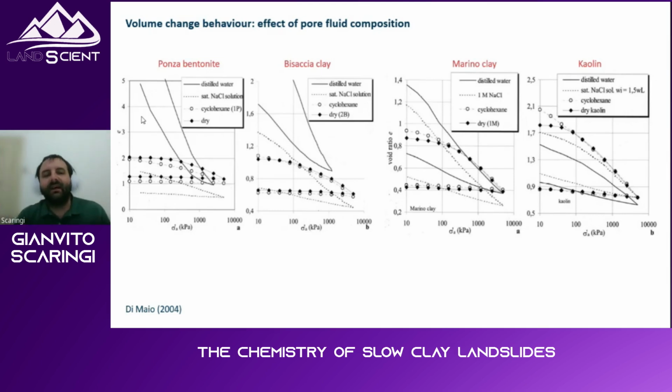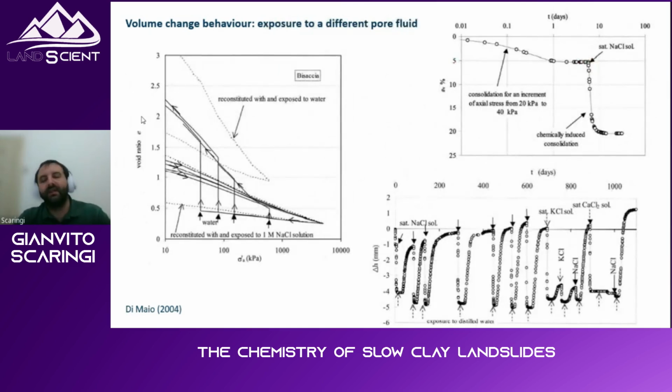So by changing the pore solution, you are changing completely the volumetric aspect and the volumetric behavior of these clays. Not only can you prepare laboratory samples with a salt solution, you can actually expose samples to a salt solution during the experiments. You could make a test in which you start with distilled water and then you expose the sample to a salt solution during the experiment. Or you can do the vice versa, which is more interesting because it's closer to a natural phenomenon.